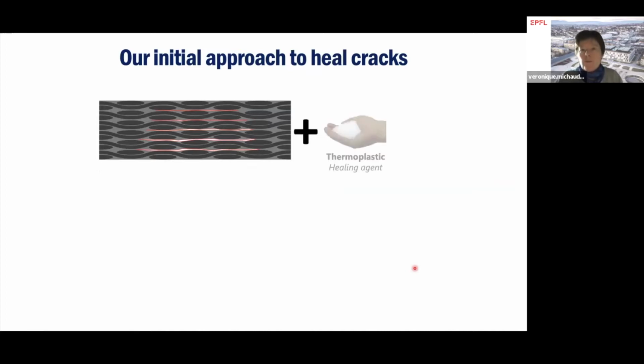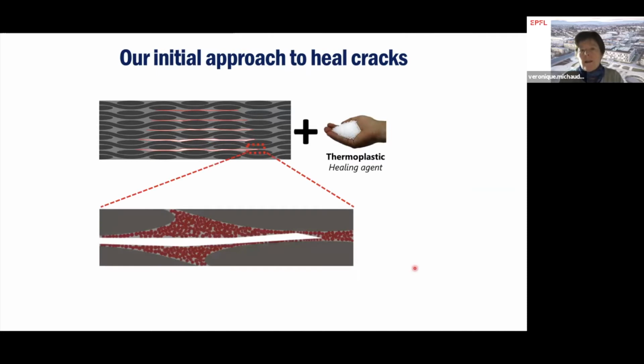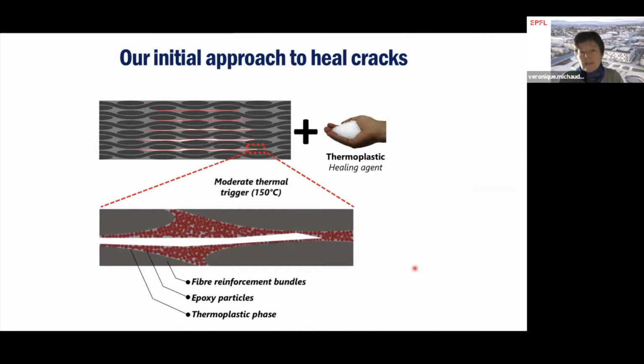So our initial approach to heal cracks was to propose to use a composite that would be load-bearing with a high volume fraction of fibers, but add a healing agent inside the composite. So if there is a crack, for example, with a matrix that has fiber reinforcement bundles, but also this matrix made of a little phase-separated thermoset and thermoplastic mixture, if the crack takes place, after a moderate thermal trigger, you will fill the crack with the thermoplastic phase that will flow into the crack and heal the crack through this phase.